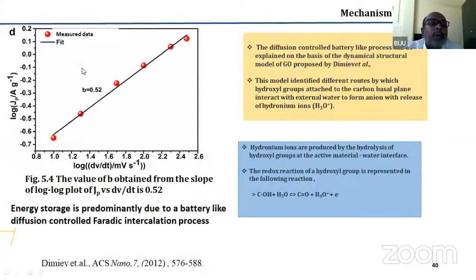Now, the other part is to analyze the energy storage mechanism. See, if the energy storage is in an electric double layer, you will get a square curve, a box-type cyclic voltammogram. But what we have obtained is not a box-type one. So we did an analysis, the details of which I am skipping. It showed that the energy storage mechanism is actually an intercalation of electrons. It is not just a surface-based energy storage mechanism. In fact, EDLC as well as the pseudo-capacitive reaction are surface-related mechanisms, where the b value in this curve, where we are plotting log current density versus log scan rate from the cyclic voltammogram, should be closer to 1. But we are getting a b value closer to 0.5, which shows that the energy storage mechanism is an intercalation or battery-type process.